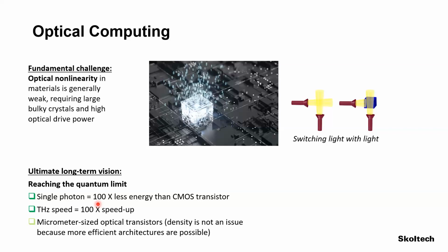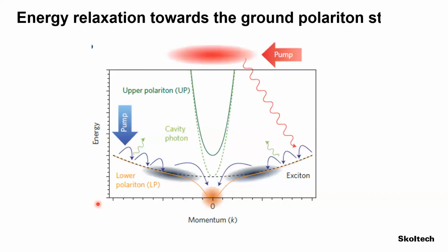Okay, so how are we going now to create this kind of optical transistors with polariton condensates? The system that we use, we inject carriers inside optically, non-resonantly. So we use a laser beam, and we inject an electron hole plasma. So these are electrons and holes, which relax in energy. This is the in-plane momentum of the cavity we were talking about. You can see here in orange the lower polariton dispersion.